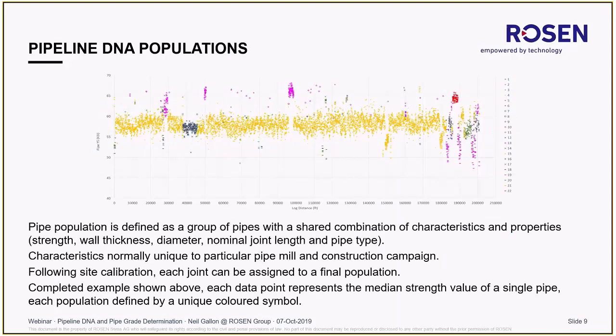The first step to doing this is to split it out into populations. These populations are defined as groups of pipes with shared characteristics. So characteristics that we'll normally pick on as the major ones are the strength, the wall thickness, the diameter, the nominal joint length, and the pipe type. So pipe type as defined in the weld type. Was it seamless? Was it longitudinally welded? These characteristics tend to be unique to a particular pipe mill and construction campaign.